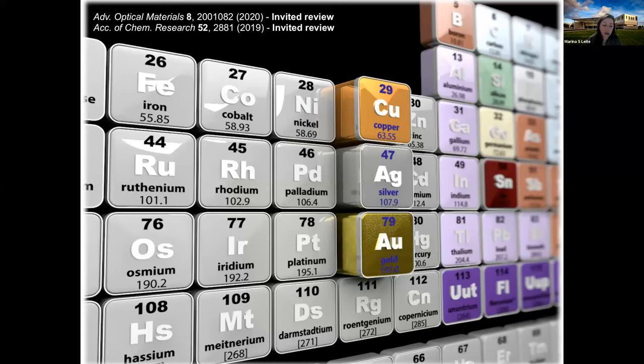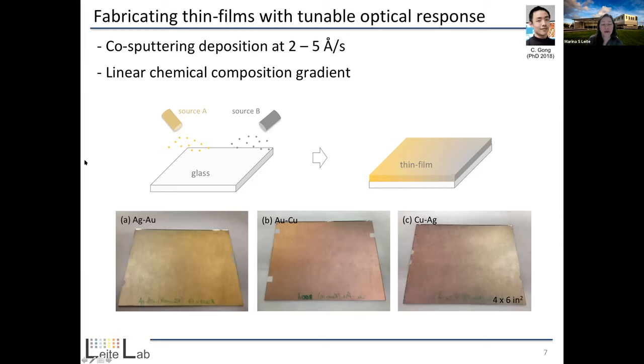So again, the ultimate goal here in the beginning was to build a library of the optical response, or the permittivity, of these binary mixtures, so that then we could provide a database that can be useful for the design of more complex types of nanostructures. And then in our optical simulations, we then have a realistic input. Because it turns out that the permittivity of these binary mixtures is very different from the linear combination of any of these two metals weighted by chemical composition. Now, we started creating this library several years ago, and we did that by making samples.